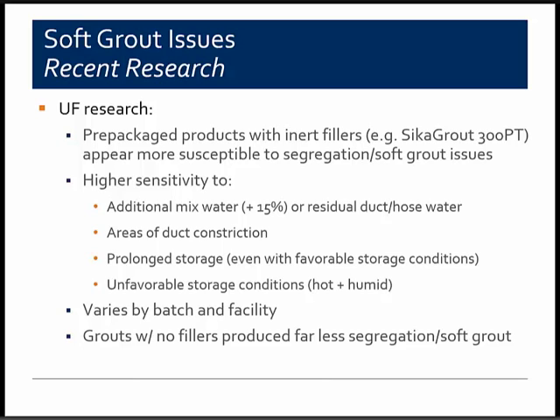And the addition of water to those prepackaged grout materials with fillers, either representing additional mixed water that was added intentionally or unintentionally, the research looked at 15% over the manufacturer's recommendations, or possibly water that's left in the tendon or the grouting equipment, again intentionally or unintentionally, consistently translated into the formation of soft grout. So when there's extra water in the prepackaged materials with fillers, soft grout was consistently produced. In addition, prolonged storage conditions, even when they were stored well, or poor storage conditions also translated into an increased rate of soft grout formation.